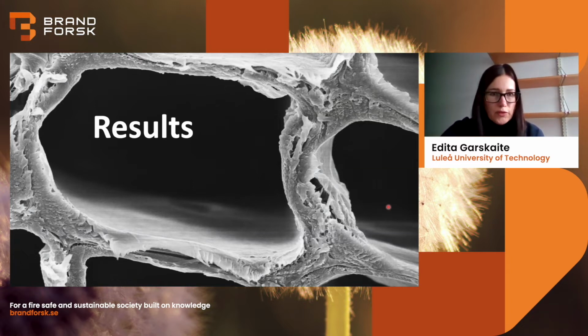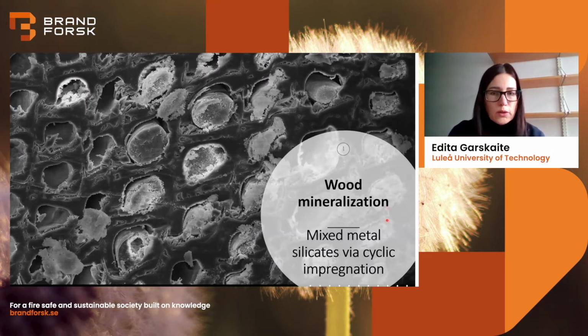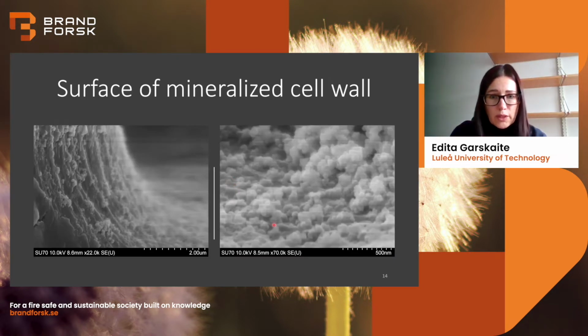Let's see what we achieved in this project. Before going into details, I would like to show one image where we had preliminary results from the previous work, where we did wood mineralization with mixed metal silicates via cyclic impregnation. And sodium silicate is actually used as a flame retardant material. So we obtained very encouraging results. We see that wood cell lumina are filled with these minerals. And here we see this so nice coverage with small nanoparticles.